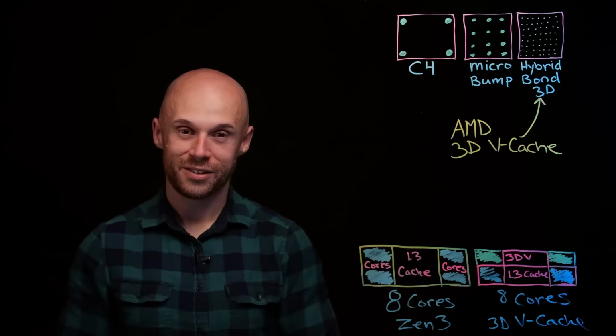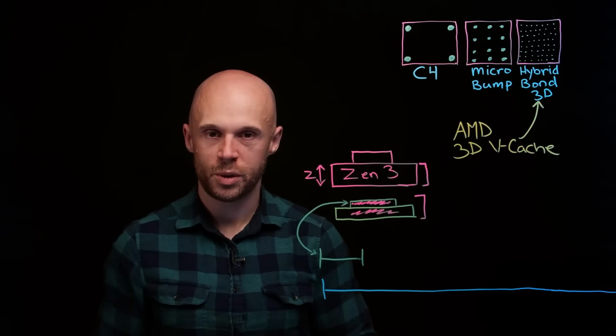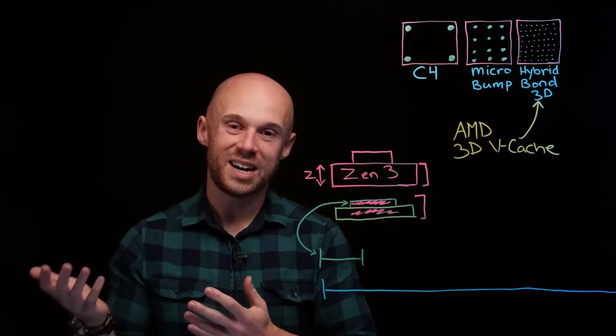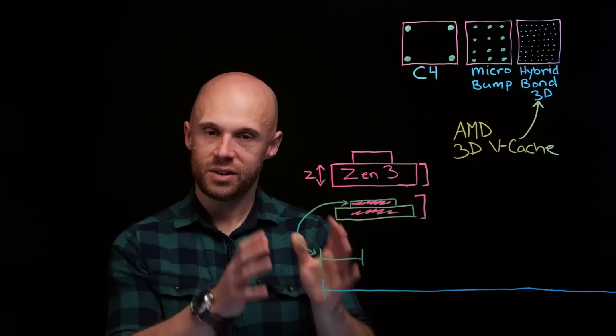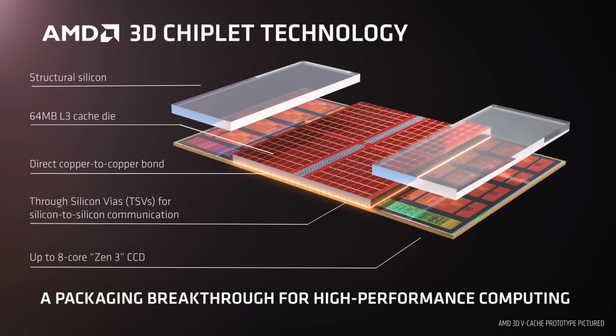The CPU chiplet, also called CCD, is on the bottom and the smaller 3D V-Cache chiplet sits on top, in the center of the CCD. Because it's not as big as the CCD, two pieces of silicon are placed next to it for structural support and to create a coherent surface. But that doesn't fit with the hybrid bonding process flow AMD is using. For Zen 3 and Zen 4, AMD uses reconstituted wafers for both the CPU chiplets and the cache chiplet.